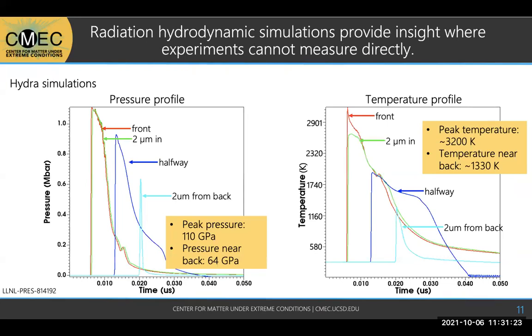So I also supplemented all this with radiation hydrodynamic simulations because they were able to provide insight where the experiments can't directly measure, i.e. the internal pressure and temperature conditions. And so we can see from the simulations that the peak pressure would occur at the front, at about 100 GPa or so. And then near the back, we have about 60 GPa. So that confirms that my design did surpass that alpha epsilon transition.